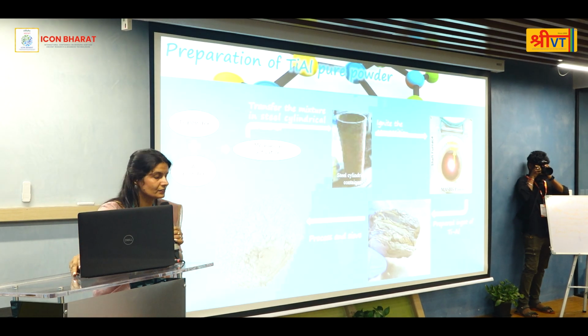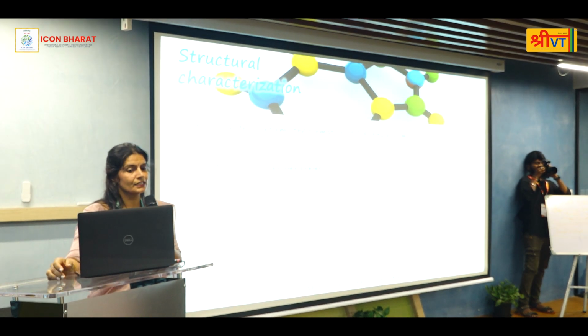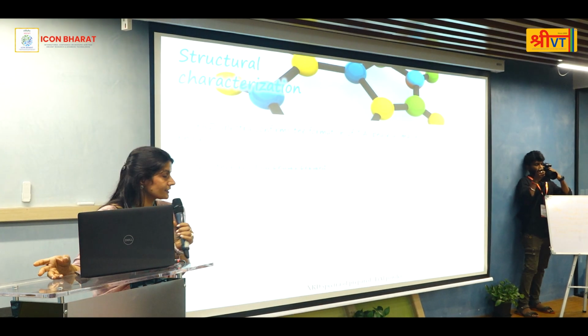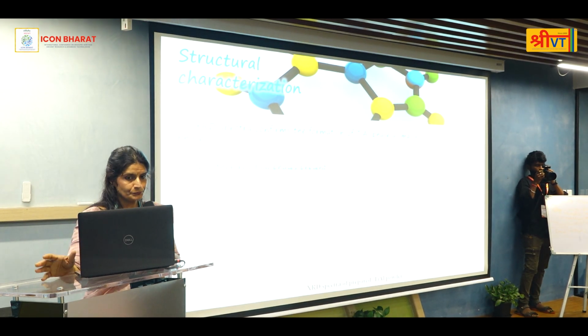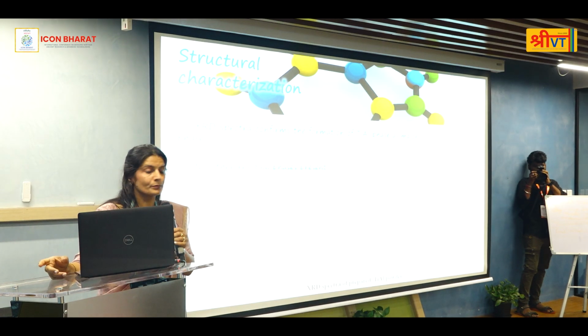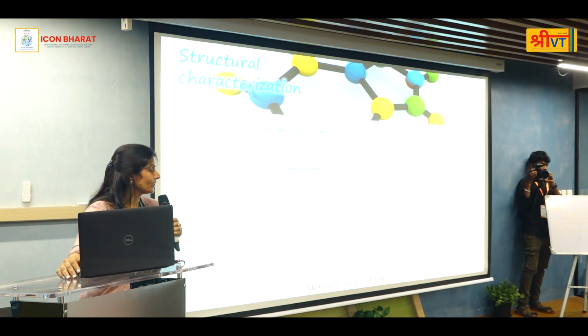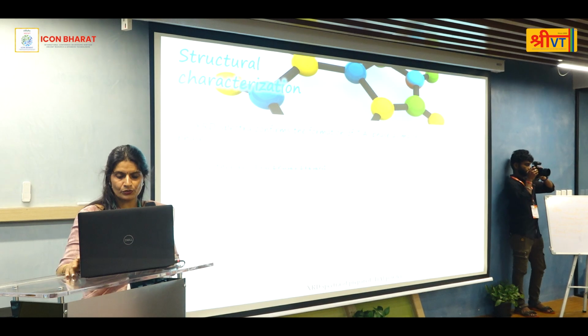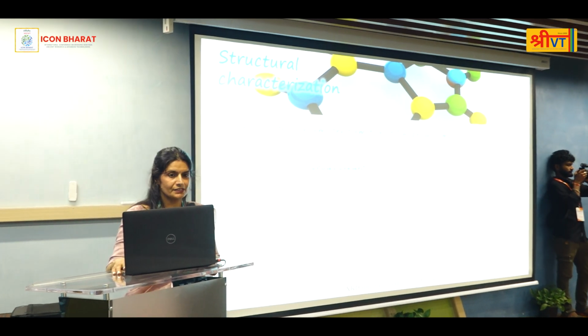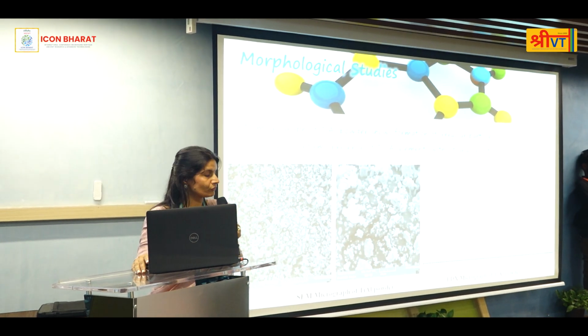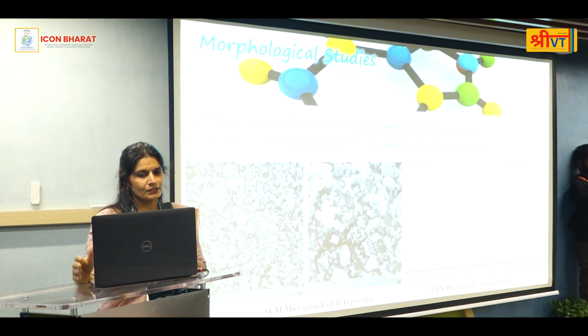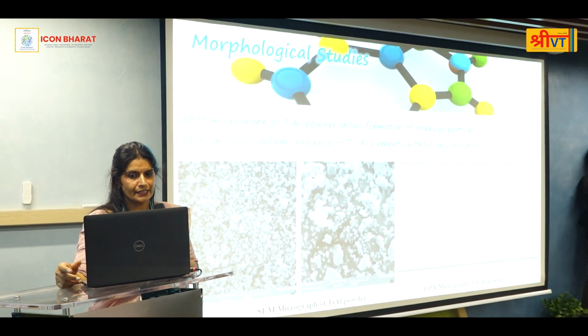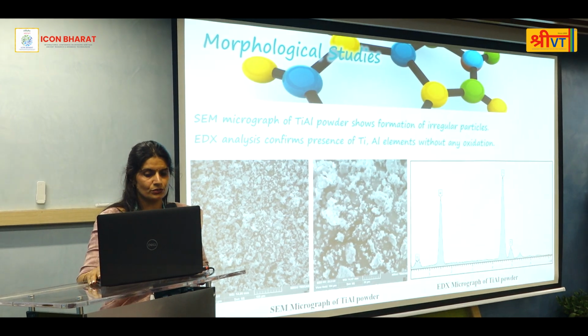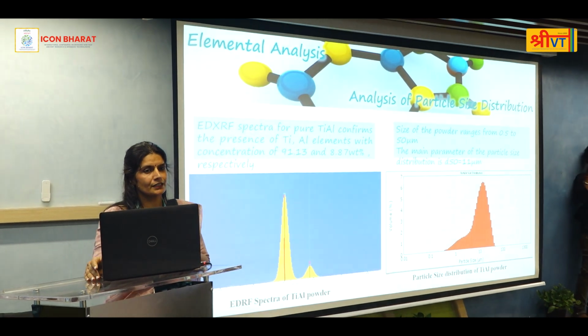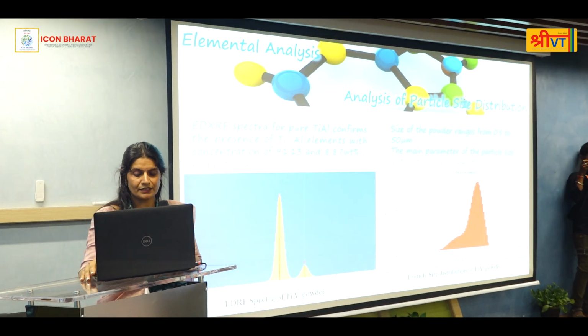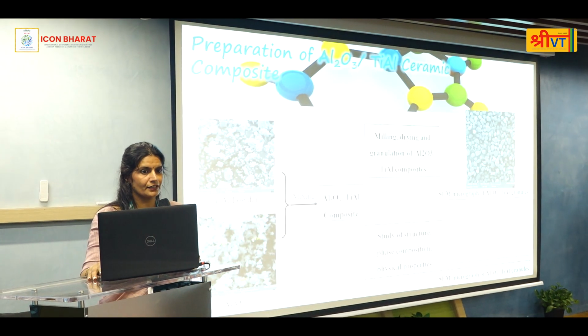Then we characterize it by various characterization techniques like XRD. The XRD spectra confirm the formation of the titanium aluminum phase as a major phase, and no residual phases are present. The morphological study also confirms the irregular shape of the powder, and the EDX micrograph confirms the presence of titanium and aluminum. Elemental analysis and particle size distribution analysis have also been carried out.